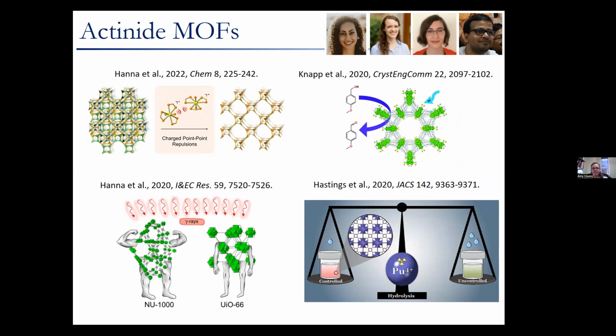So most recently, Sylvia Hanna was able to investigate a uranium MOF, as shown in the upper left-hand quadrant of this slide here. This is a uranium-based MOF. And normally, the structure on the left is what is favored at equilibrium, this highly interpenetrated series of MOFs. And that's because that minimizes the void space. And that's normally what is thought of as being the most thermodynamically favorable.